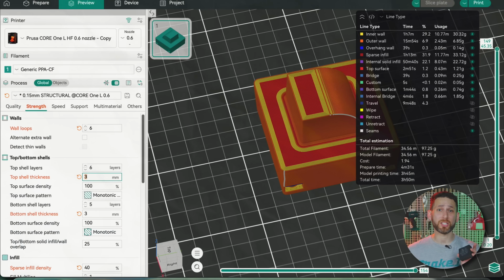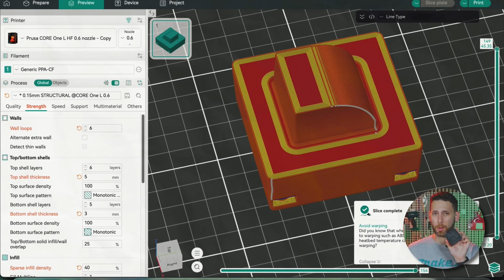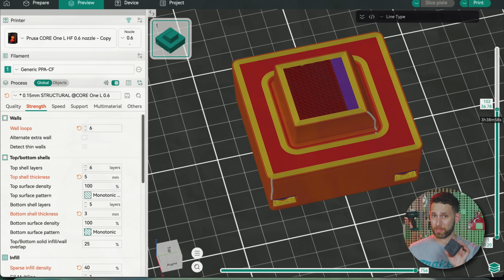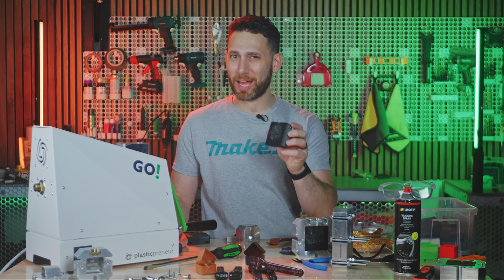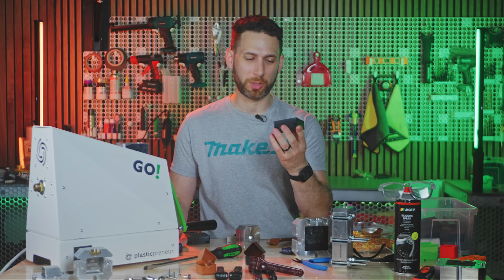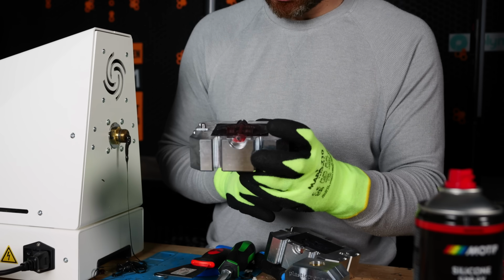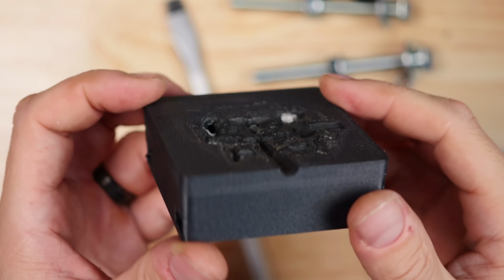I also found that unless you print with extremely thick top surfaces, like 3 to 5 millimeters thick, it doesn't actually matter if the filament is rated to withstand 200 plus degrees Celsius, because it will deform under the pressure after 1 or 2 shots, causing massive flashing.